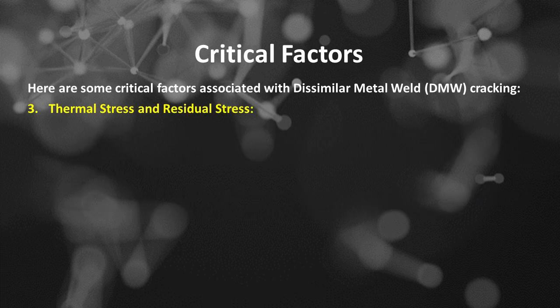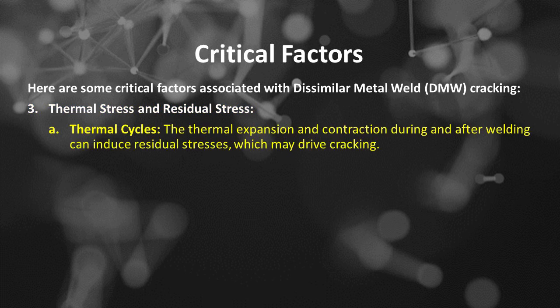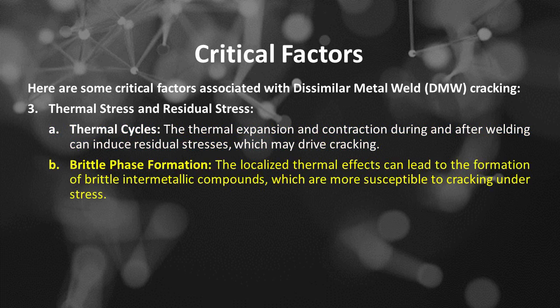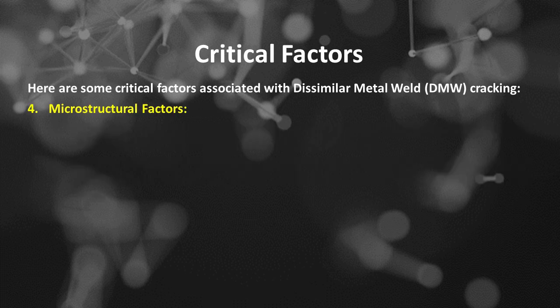Number 3 is thermal stress and residual stress, such as the following. The first is thermal cycles. The thermal expansion and contraction during and after welding can induce residual stresses, which may drive cracking. The second is brittle phase formation. The localized thermal effects can lead to the formation of brittle intermetallic compounds, which are more susceptible to cracking under stress. Number 4 is microstructural factors such as the following.